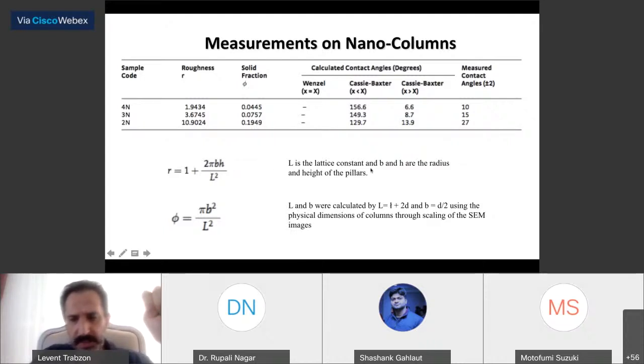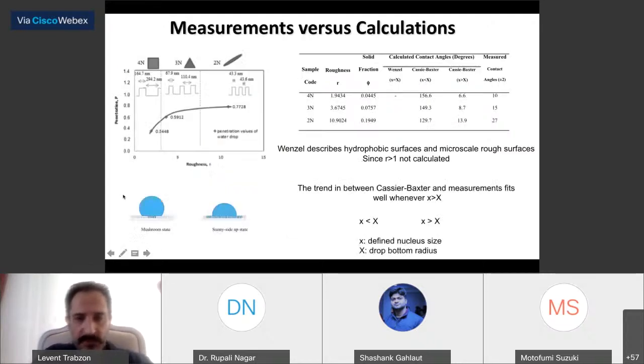L is the lattice constant, and B and H are the radius and height of the pillars, respectively. And the solid fraction is also calculated, pi times B squared divided by L squared. L is calculated using the periodic lattice approach, I mean the distance in between, plus 2D, the thickness of the columns, and B is D over 2. Based on those numbers, we end up with the calculation of the roughness and the solid fraction in each case.